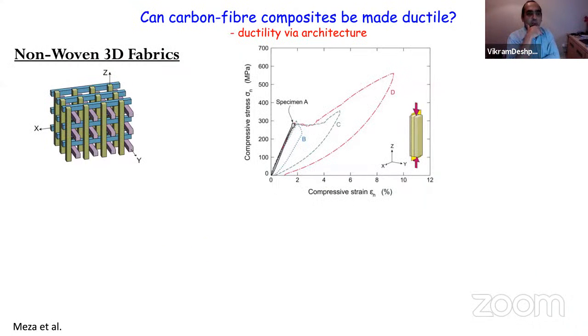So the question is, can you make carbon fiber composites more ductile? That's a tricky situation, because the carbon fiber itself has 2-3% ductility at most. So how can you make carbon fibers more ductile? Again, we will try to see whether architecture can help here. We're thinking of a composite which is 3D but non-woven. So you have tows in 3 orthogonal directions. I would not even call it woven. It's what they call in the carbon fiber literature, noobed, basically. They're just interlaced in some ways in this manner here.